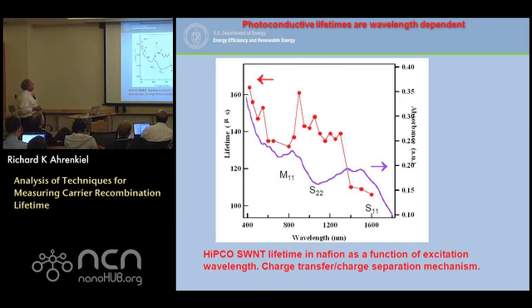To show the versatility of the RCPCD, the late Ann Dillon was making single wall nanotubes in a Nafion binder, and just for the heck of it, we ran it in the RCPCD. And actually we have very long lifetimes, and I'm not going to attempt to explain these at all. The lifetime being in microseconds, so some kind of a charge separation. The complexity in carbon nanotubes is beyond me, but anyway, we were able to measure a long lifetime over a wide wavelength range. Maybe carbon nanotube people can explain that. Unfortunately, Ann has passed away.